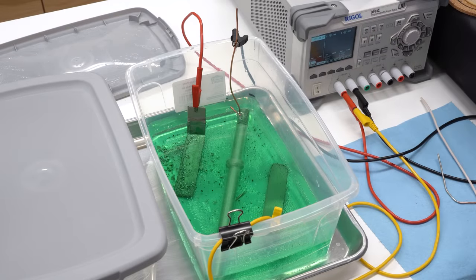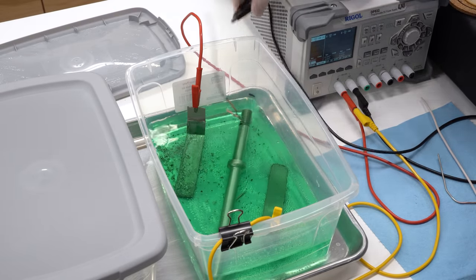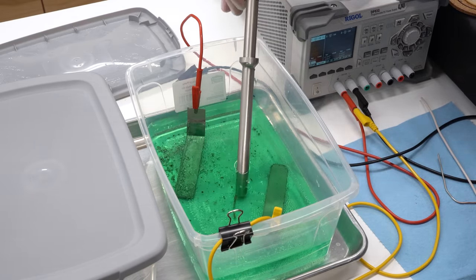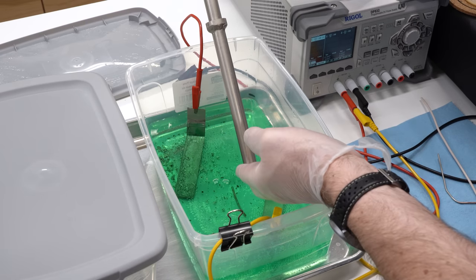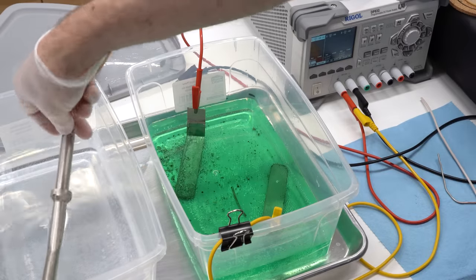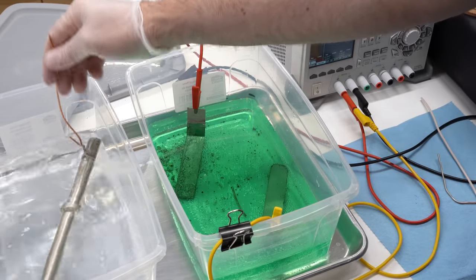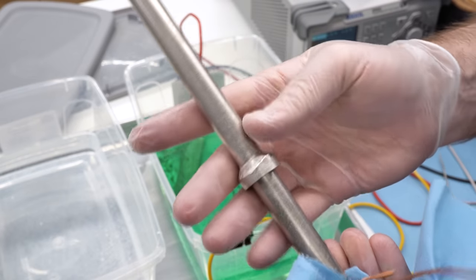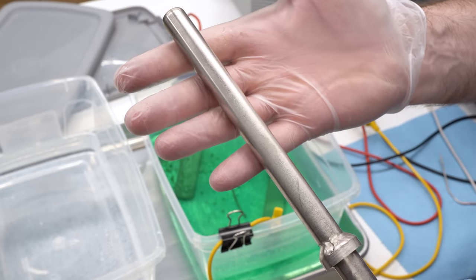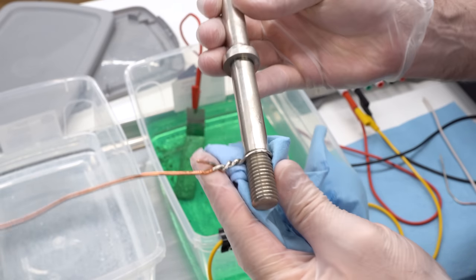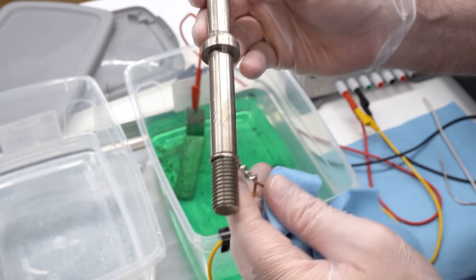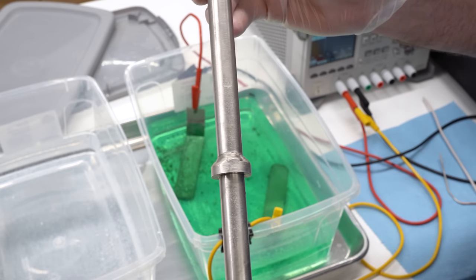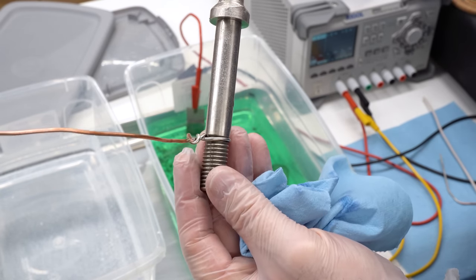Okay, it's been about 30 minutes. Let's turn off the power supply and pull out the part. Take off the negative electrode there and have a look at this. It does appear to be plated. It doesn't look like steel anymore. It's a nice, even silver color. It's not quite as shiny as I expected. Let's get this rinsed off. This is just some plain tap water. Looking at this a little closer, it sure is pretty. It's not as shiny as I expected. It's a little bit more of a matte finish, but the plating is really quite even. A lot more than I expected. You can see the wire there is definitely plated. I'm not sure how well it's plated down in the threads, though that doesn't really matter. It looks like I've got good coverage. It looks like I've got good adhesion. It is nice and shiny on that wire. Look at that.